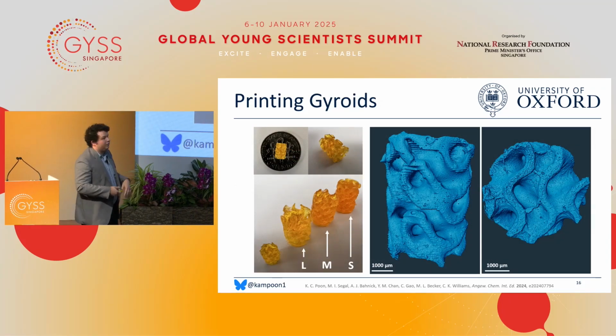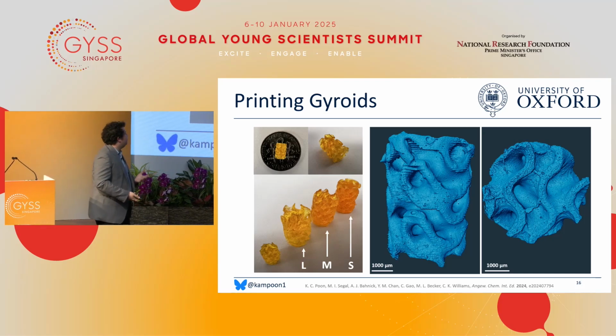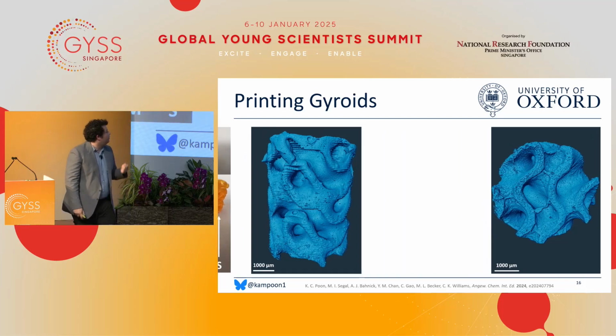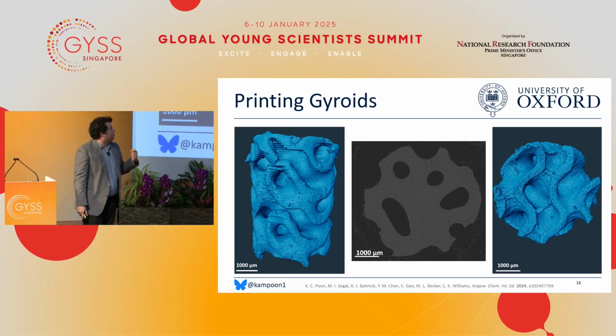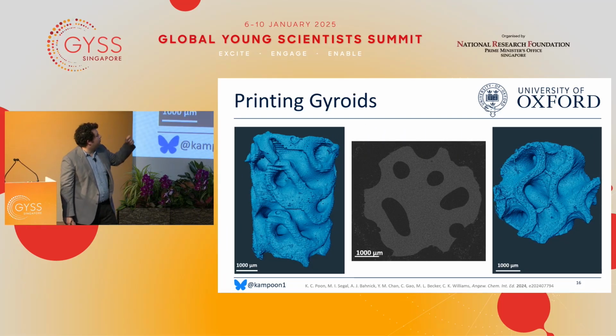Finally, we wanted to test how good the resolution was that we could achieve with this resin. So we printed some more fun structures, in particular these triply periodic gyroids. You can see the smallest one here is just 3 millimeters tall. And here in the CT scan of it, you can see that we maintain really good resolution of these small details, in particular the internal holes and cavities.